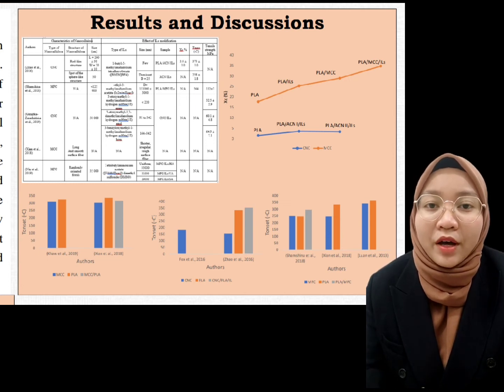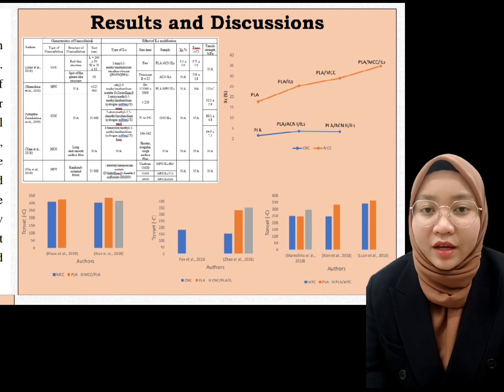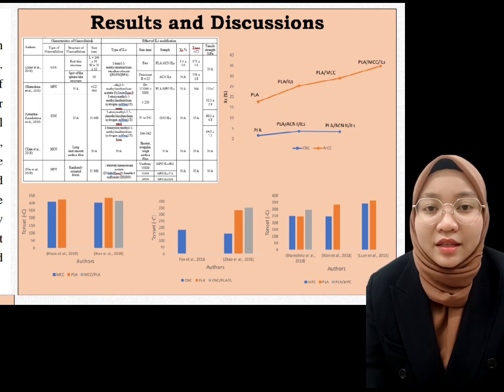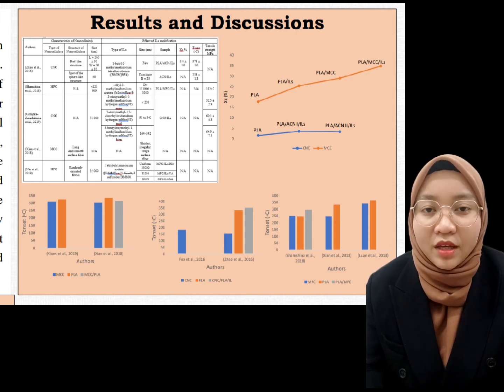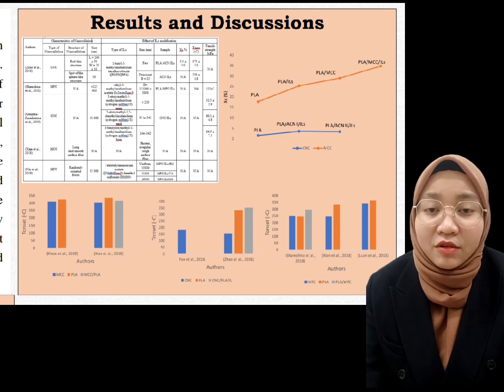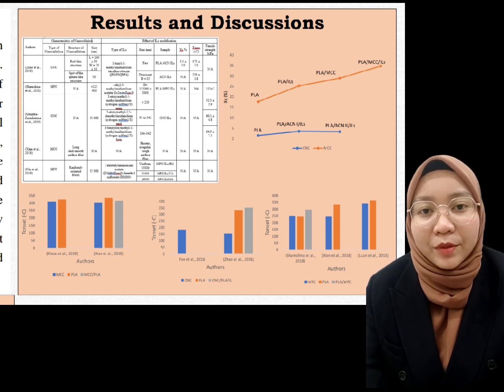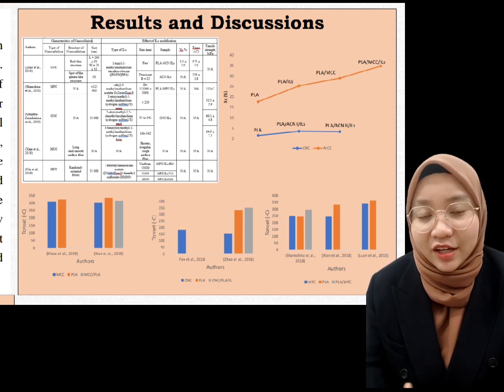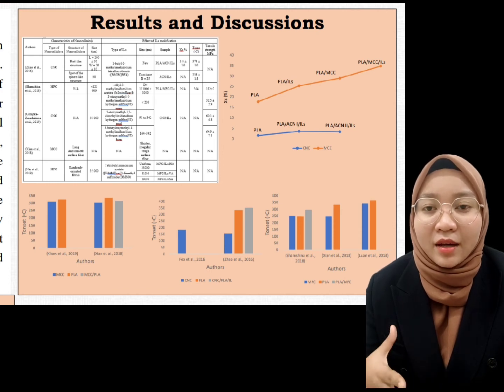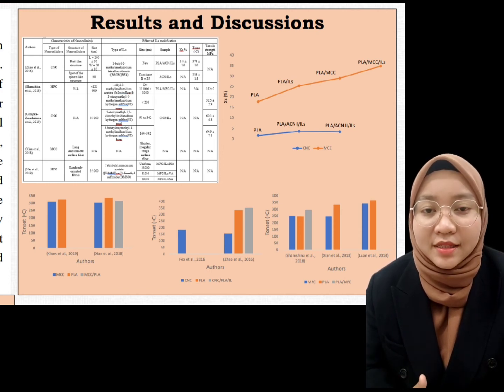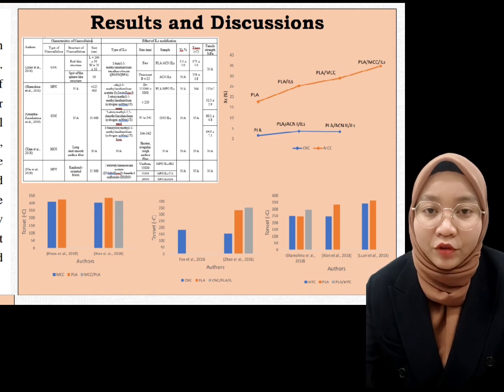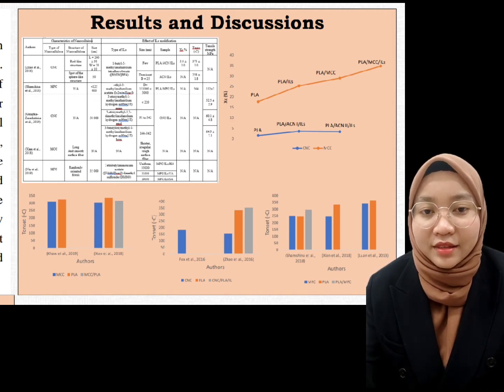The cation type of ionic liquid also has a significant impact on the particle size and dispersions of cellulosic material manufacturing. The specific surface area of cellulosic fiber will be larger if the particle size of the cellulose fiber is small, which will enhance the characteristic. So the table shows the comparisons of the size before modification with ILs and after modification with ILs.